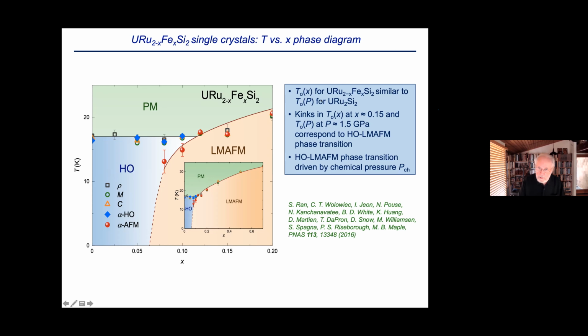Okay, so this is similar to the phase diagram that I showed you earlier under pressure. There are kinks in this phase boundary at about 0.15 for X, when you go from the hidden order phase to the large moment antiferromagnetic phase along this phase boundary. And the pressure at which this occurs with the undoped sample is 1.5 GPa. One early interpretation we made was that this appears to be driven by chemical pressure, because the reduction in the unit cell volume that would give rise to this phase diagram is similar to that which would occur under pressure. And so we thought that was simply the reason driving it. I mean, pressure drives it, so we could assume that chemical pressure would basically do the same thing.